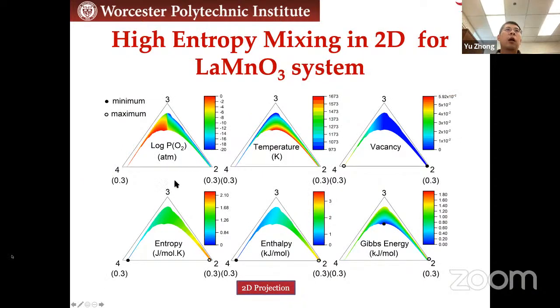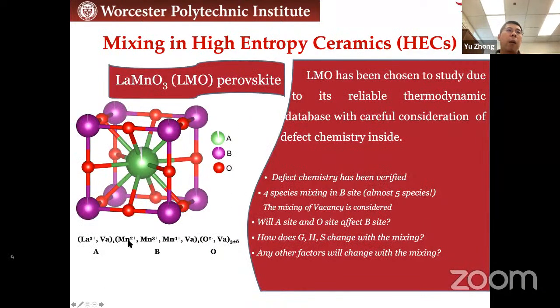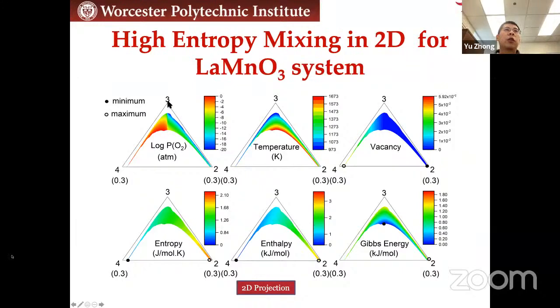For example, here we have manganese 2+, 3+, 4+, and vacancy. They mix on the B site for LMO, which is a very simple oxide. This shows how they mix together, and in which condition, corresponding to oxygen partial pressure, temperature, and vacancy, and also the thermodynamic properties: entropy, enthalpy, and Gibbs energy. With this, people can get a very good idea of what is happening.